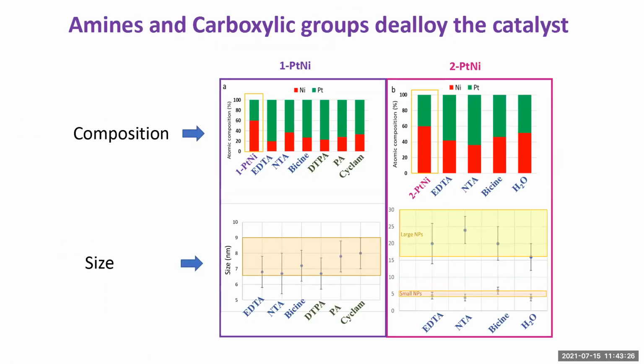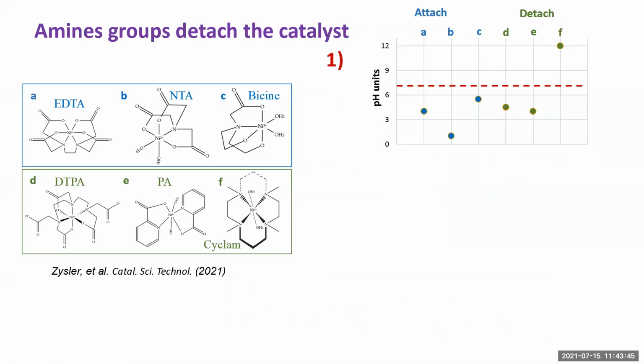So first of all, the composition of the particle will change, and it is very dangerous if nickel goes out from the particles, because it not only decreases the activity, but also creates poisoning all around. And the size also changed a little bit, not so much. So we wanted to know why some chelating agents detach the particles and why others do not.